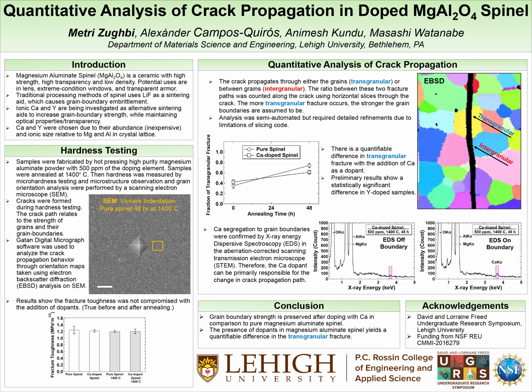Overall, grain boundary strength was preserved after doping calcium and yttrium in spinel samples, and the presence of these dopants did contribute to a quantifiable difference in the amount of transgranular fracture and the crack propagation of magnesium aluminate spinel samples.